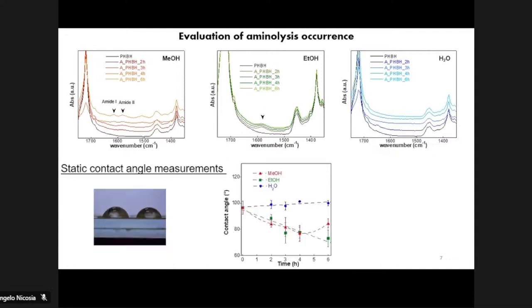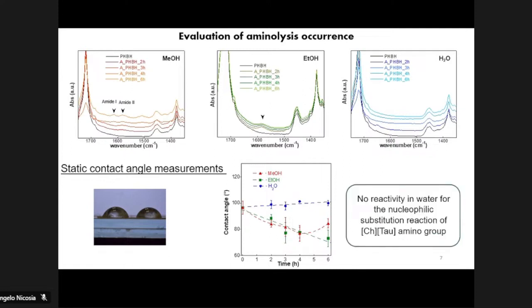These observations were also confirmed by contact angle measurements, with decreasing values for samples aminolyzed in methanol and ethanol and quite constant values for samples aminolyzed in water. These results lead us to conclude that water is not a good solvent for aminolysis, since the amino group of choline taurinate is protonated, resulting in no reactivity for nucleophilic substitution.